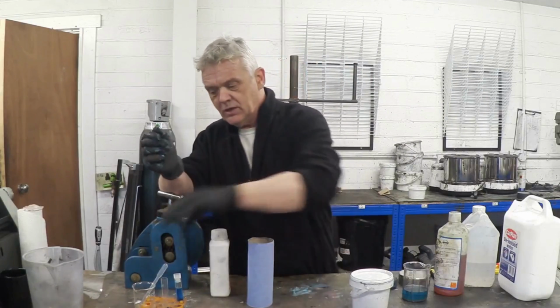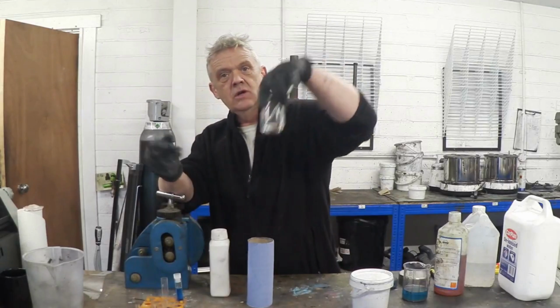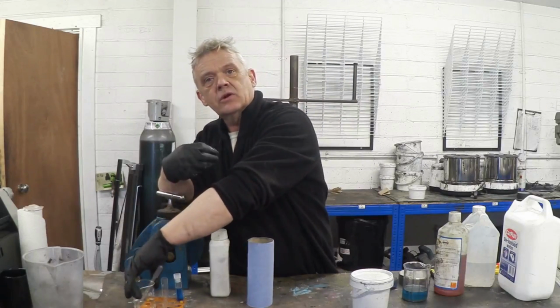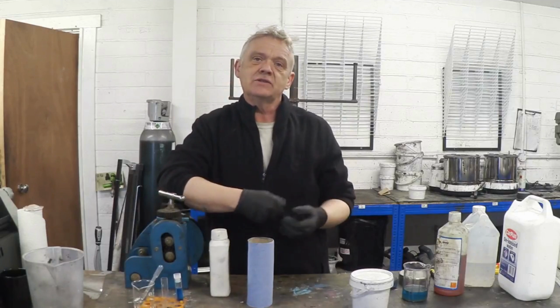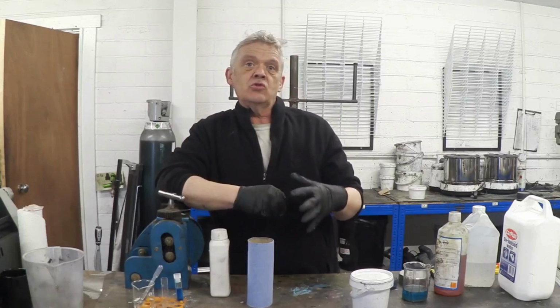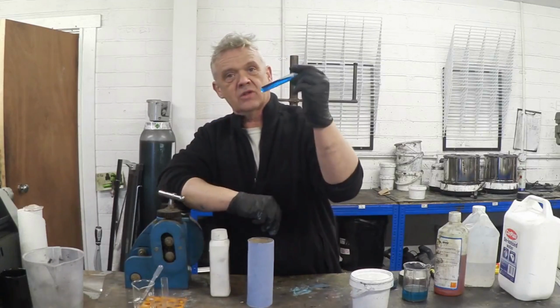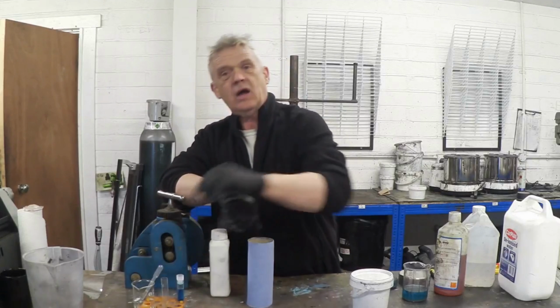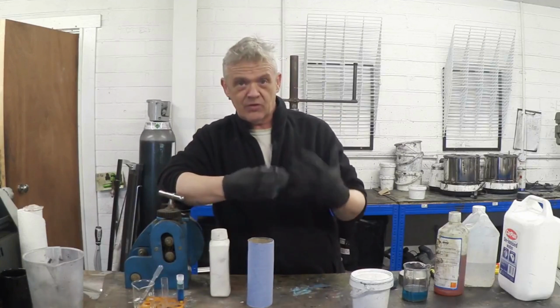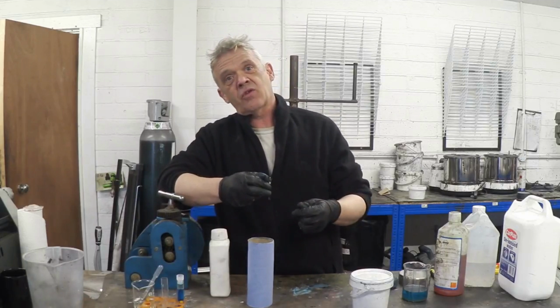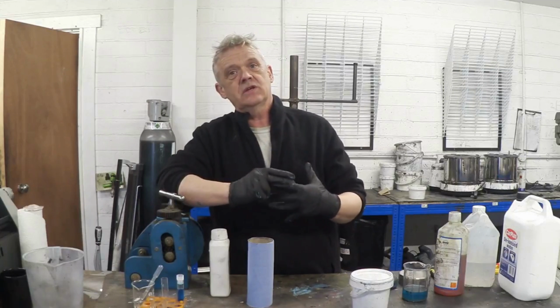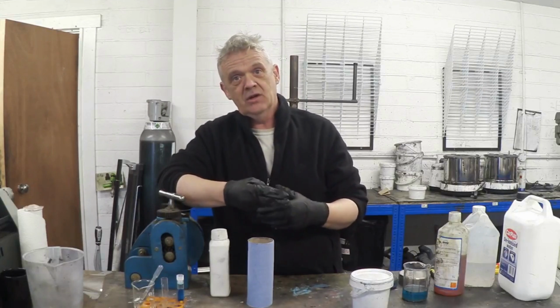Once you've printed it and dried it and you put a spot of this material, it reduces straight back to the copper, so you can print copper lines on paper using a two-pass method, once with the ink, once with the developer, and out comes the copper lines, and we'll do a video on that as well. Another thing you could do with it is you could mix it with some graphite or some carbon.